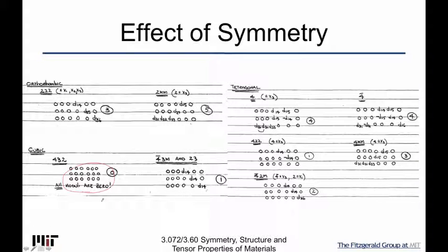And so a 432 group cubic symmetry cannot have piezoelectricity. And for the other cubic groups 23 and 4 bar 3m, you actually can, but it's very restricted. There's only 3 to worry about. And so on. You can see here the tetragonal case.